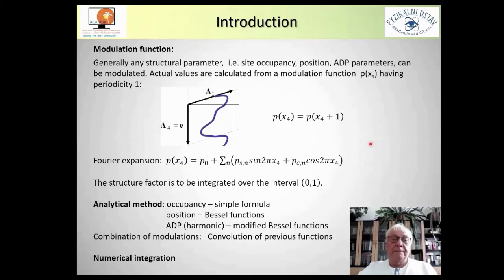The structure factor is to be integrated along this line again from x4 0 to x4 plus 1, and this process is time consuming. We can use analytical methods, which means that for occupancy, in fact, we have a very simple formula. For position, it's a little bit more complicated. We have to use Bessel function. And for ADP parameters, we have to use the so-called modified Bessel function. However, if we have a combination of all these effects, or if we have more than one harmonic, then this analytical method is very difficult because we have to make convolution of all previous functions. For this reason, we prefer the numerical method, where we make integration along this line numerically.